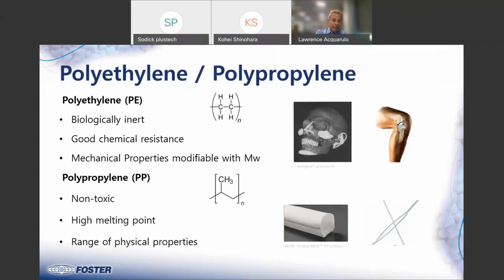Polypropylene, the same thing. Non-toxic material, a little bit higher rigidity than polyethylene, but it does create some kind of a flexible hinge type property, which is important in certain applications, certainly in these woven meshes. It seems to have pretty good application. And these materials are readily moldable, injection moldable.